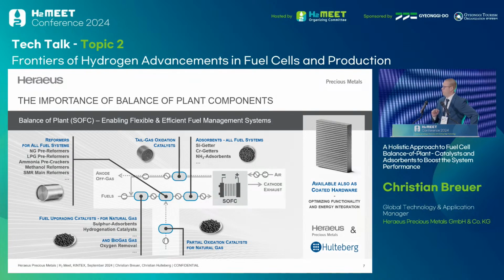And then of course we have the different reformer systems. Pre-reformers for natural gas, for LPG. We can use ammonia pre-crackers. We can use methanol reformers. And then, additional to the pre-reformers, there are also the classic main reformers, especially for SMR, for example, classic steam methane reforming options. And then, on the outlet side, there are the tail gas oxidation catalysts for the anode off-gas oxidation. But on the inlet, there are the getter materials that prevent, or should prevent, silica or chromium that is forming in the system from getting into the stack.